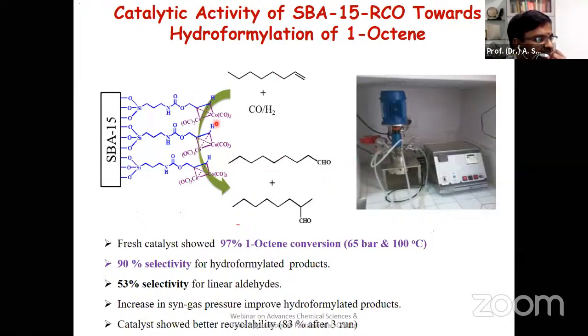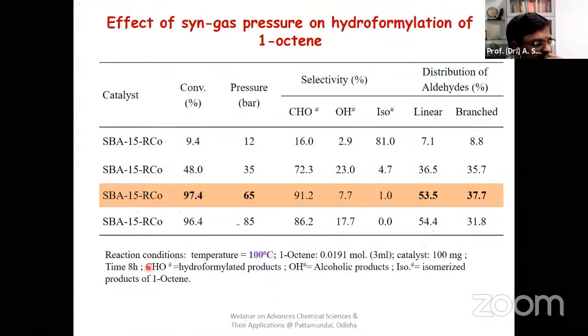You can see that this kind of complex gives 97% conversion. It is carried out in the liquid phase with the heterogeneous catalyst, in a high pressure liquid bed reactor, for 8 hours at 100 degrees centigrade. We can see that the catalyst can convert the olefin into hydroformylated product at about 97%. It is carried out at 65 bar. Sorry, not 100 bar, 65 bar. It gives 97% conversion with hydroformylated product 91% and hydrogenated product alcohol 8%. So you can see that these are the product distributions.